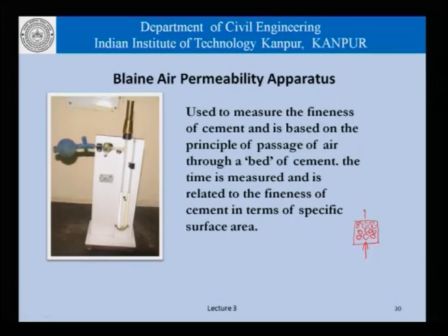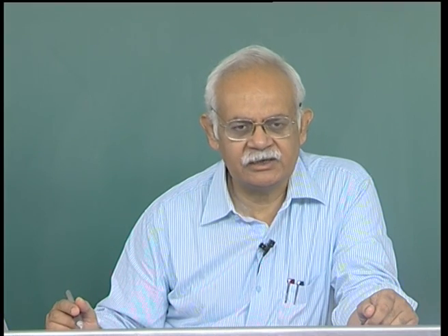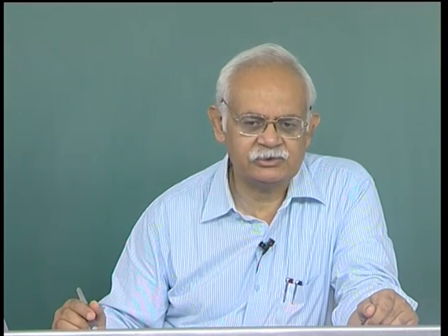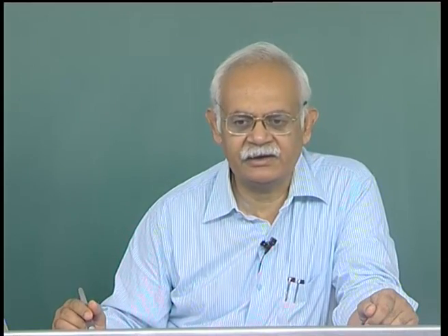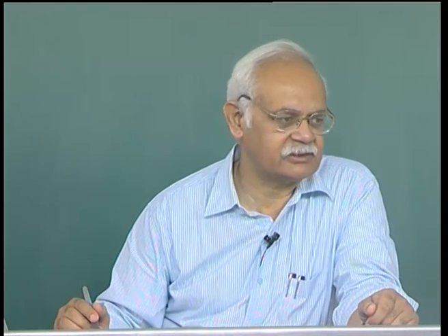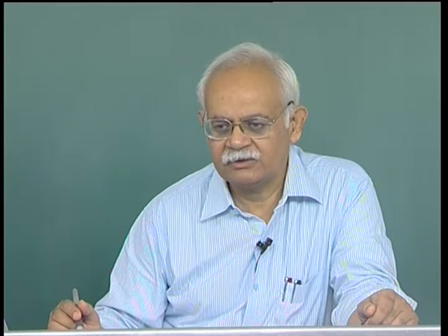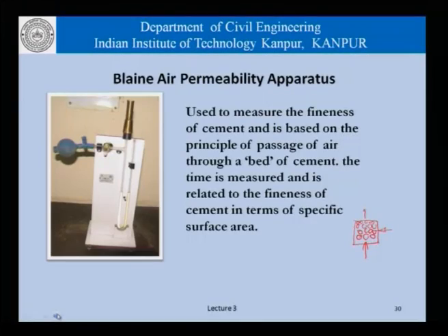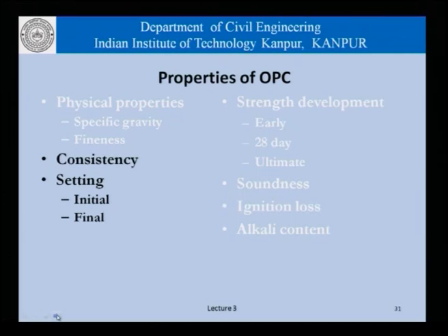We have the air pass through such a bed, this is what is called the bed, and the time it takes is recorded. This time is related to the fineness of the particles that we use. There is a calibration curve using standard powders, and it is used to estimate the fineness of cement. There are other methods as well, and I am leaving that out as a self-study project.